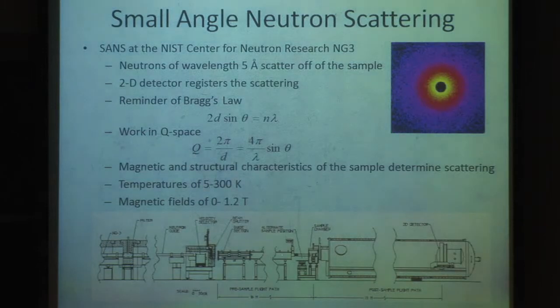Our measurements were done using small angle neutron scattering. This method was done at the NIST Center for Neutron Research, the NG3 beam line in Maryland. There, 5 angstrom neutrons were scattered off of our sample, and we detected them with a 2D detector. Our detection looked something like this, where the bright spots, such as the yellow, were a lot of counts, and the dark spots out here were very few scattering counts. This is like a reminder of Bragg's law, where 2d sin theta equals n lambda. But we don't like to work in such things as d or theta.